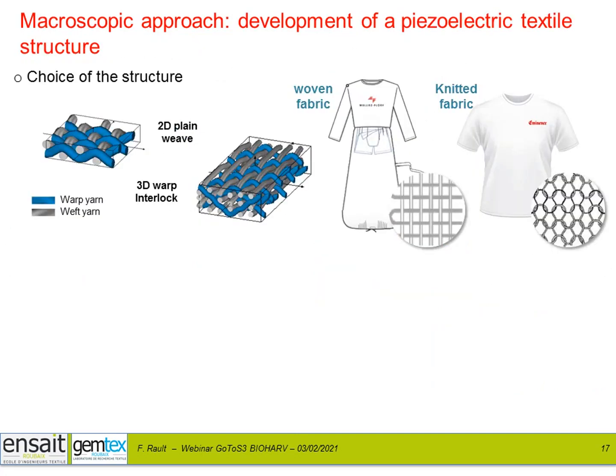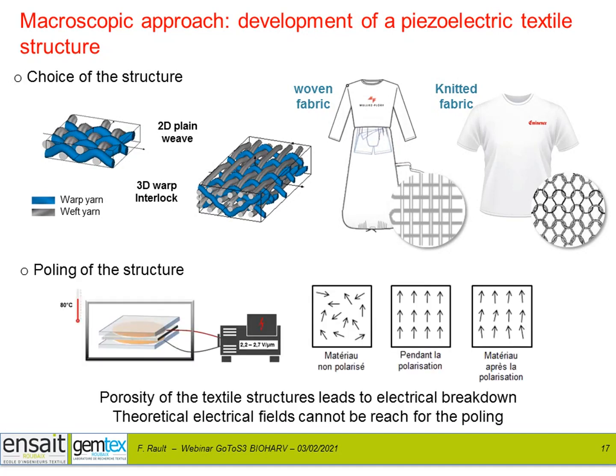For the macroscopic approach, we use 100% PVDF filaments with an optimized beta phase content. We worked on the choice of the textile structure to be able to solicit the maximum of filaments during mechanical stress. Our objective is to harness the maximum of electrical charges. Before testing our structures, we carried out polarization tests on these textile structures. Unfortunately, the porosity of these woven or knitted fabrics causes electrical breakdown, and the theoretical electrical fields cannot be reached for the poling.